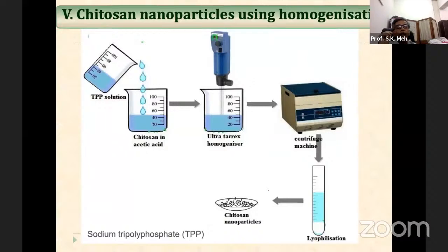You can also create chitosan nanoparticles. Chitosan nanoparticles are also a very good one. So you use here sodium tripolyphosphate, and you take chitosan in acetic acid, and using a homogenizer, centrifugation and lyophilization, you can get the chitosan nanoparticles. Chitosan nanoparticles are also very important from a biological point of view. They are acceptable up to a certain concentration range, and they are not toxic, and therefore one can use these for biological purposes.